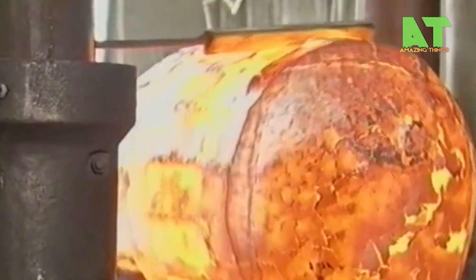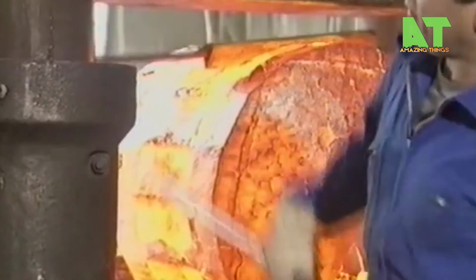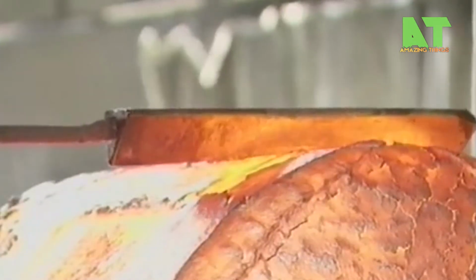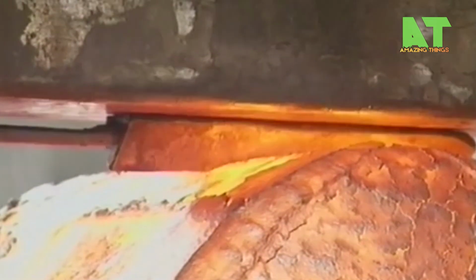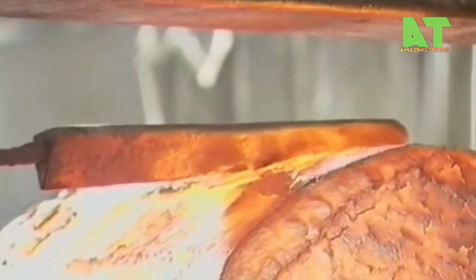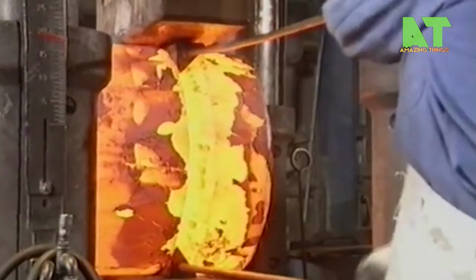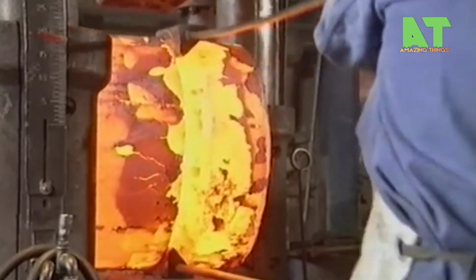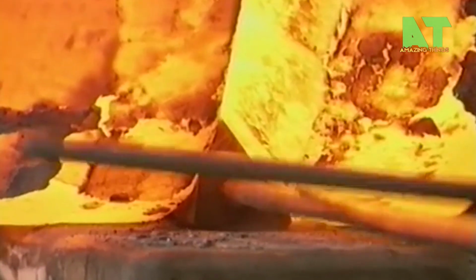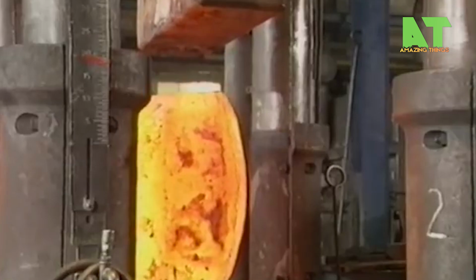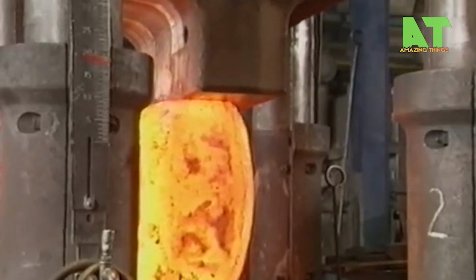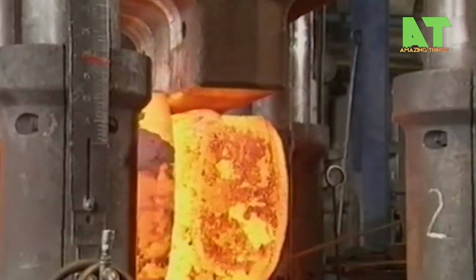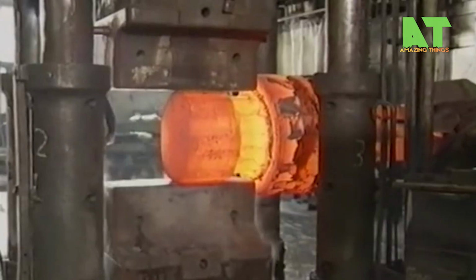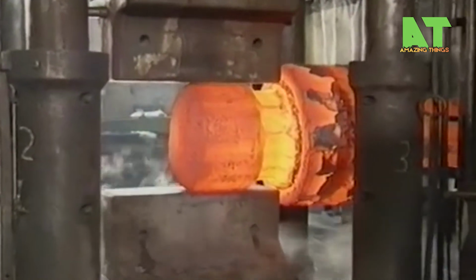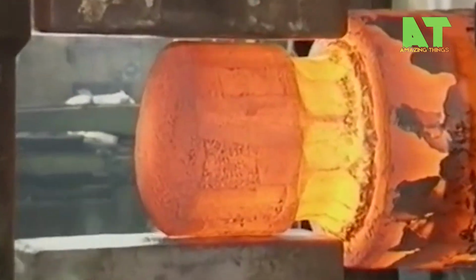Now we're seeing ring rolling, which is absolutely mesmerizing once you understand what's happening. That heated ring blank is being fed between rollers that are simultaneously compressing and expanding it. The main roll applies pressure, reducing the ring's wall thickness, and as the metal has to go somewhere, the ring grows in diameter. It's like rolling out pie dough, except the dough is glowing steel at 2000 degrees. The beautiful part is how the grain structure flows circumferentially, creating a ring with exceptional strength in the direction it needs it most. These rings often become bearings, flanges, or pressure vessel components.